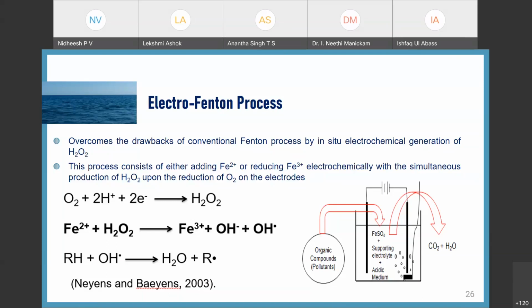We know that Fenton reactions take place at acidic pH. So we took these conditions as an advantage in the electro-Fenton process. That means if you are using a carbonaceous cathode and aerating in acidic condition, which is required for the Fenton reaction, the 2-electron cathodic reduction of oxygen will take place and form hydrogen peroxide near the cathode. So if you add some ferrous sulfate to this system, hydrogen peroxide will be generated by the aeration, and Fe2+ will react with H2O2 to form hydroxyl radicals. That is the advantage of the electro-Fenton process compared to the conventional Fenton process.